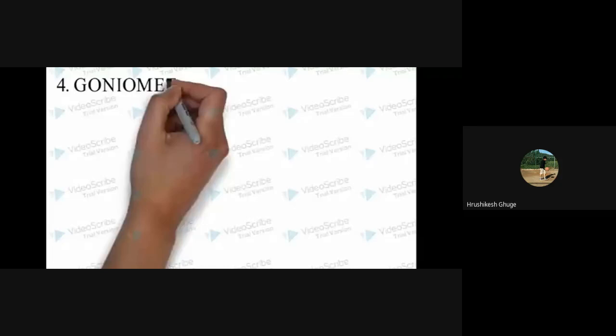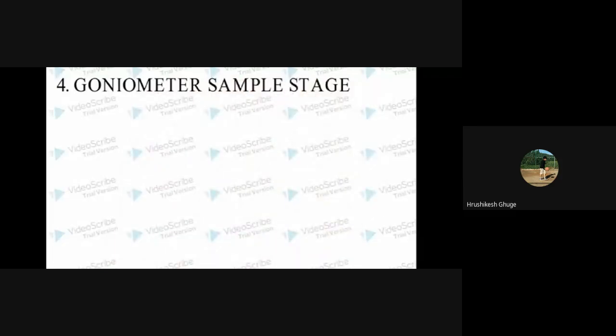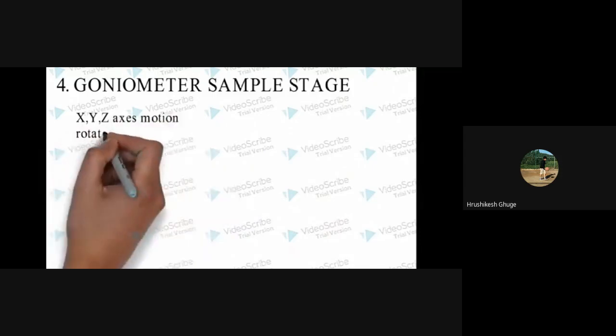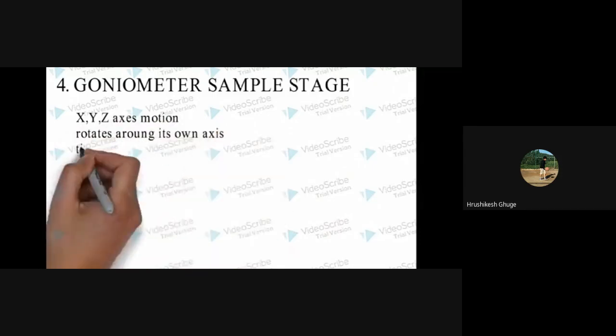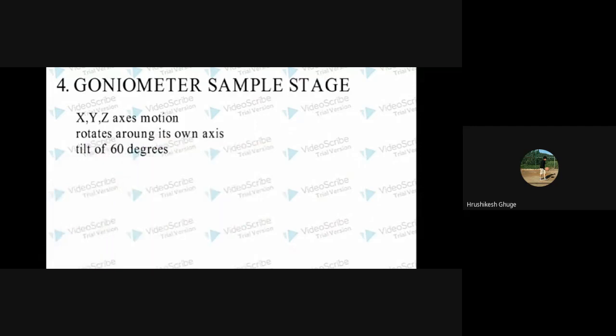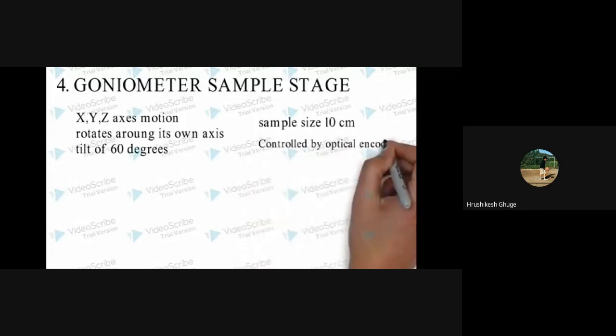The goniometer sample stage, that is the stage on which the workpiece is held, can provide three-dimensional motion along x, y, and z axis, and it can rotate around its own axis. Also, it can tilt the sample up to 60 degrees if required. This is the standard stage which is used in many machining processes. It can handle a size of approximately up to 10 centimeters depending upon the chamber size. The position of the sample stage is controlled by optical encoder with high precision.